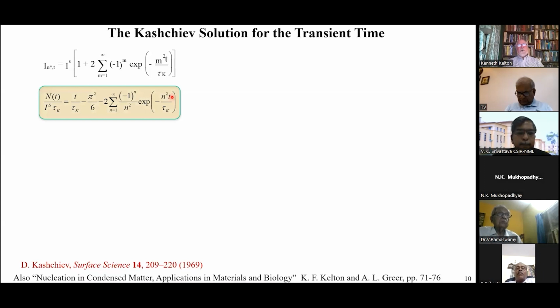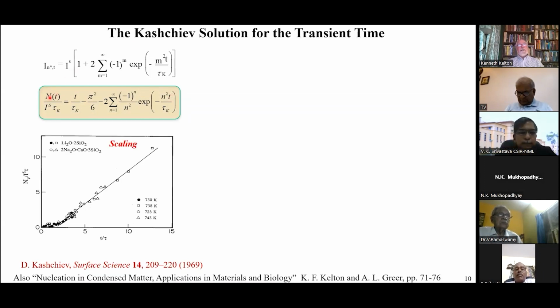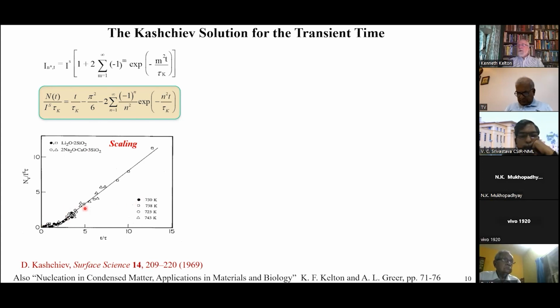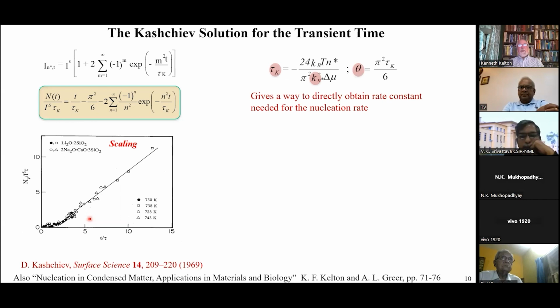What does that mean? Well, if you look at it, it says that if I make this plot the number divided by the steady state rate multiplied by the transient time as a function of t over tau k, I get a universal curve. So what he predicted a universal curve, and if you go back and look at a variety of different silicate glasses for different nucleation temperatures, you find that they do indeed follow that curve. So that's a very powerful theorem, a very powerful expression.